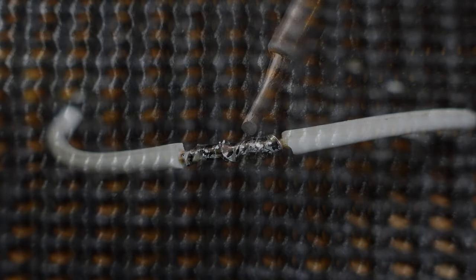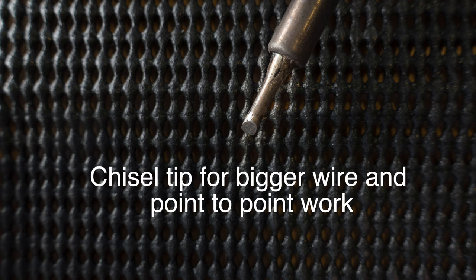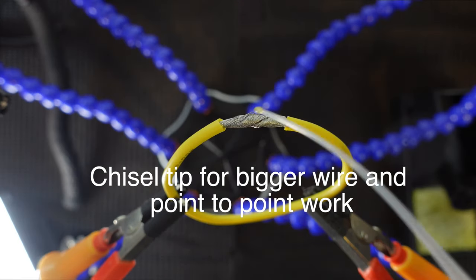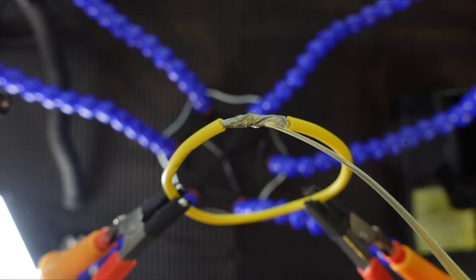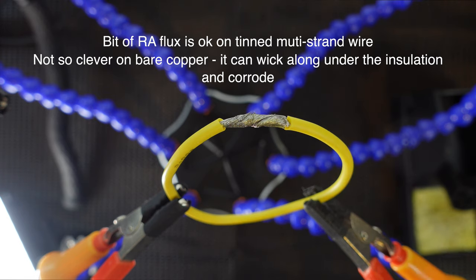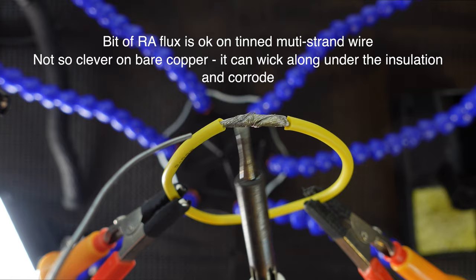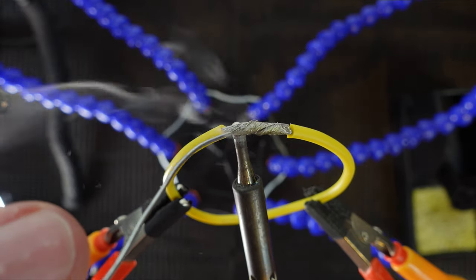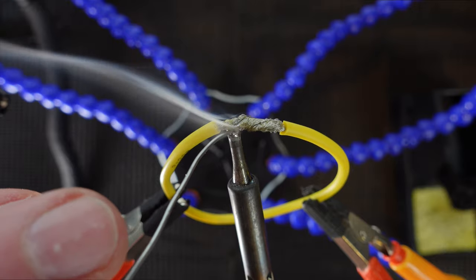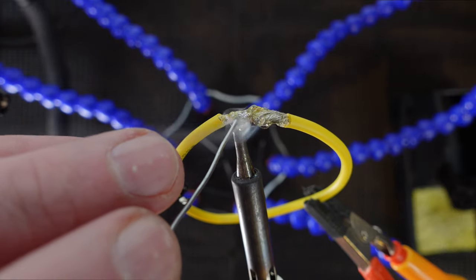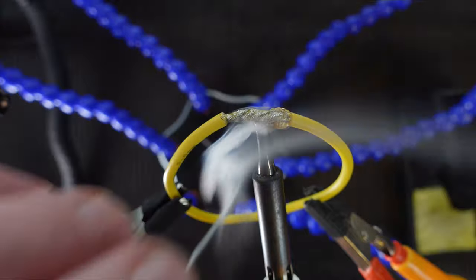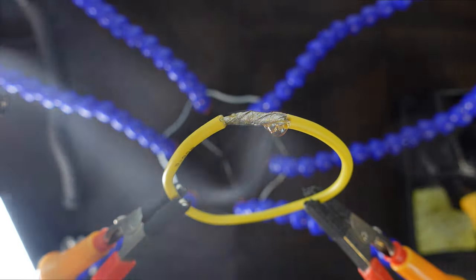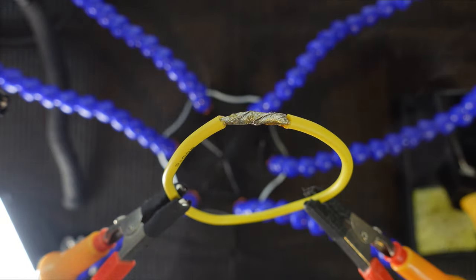This guy is what I use for maybe automotive or boat work or just bigger wires, basically. The RA flux helps. If you linger too long and heat the wire up too long, that flux can actually wick down below the insulation. If you're doing this on copper-stranded wire without the tinning like in this case, that RA flux can go down inside the insulation and it will turn it green and corrode because of the very nature of flux.